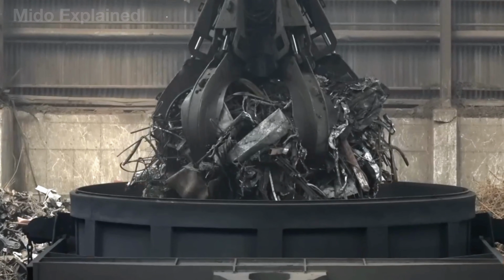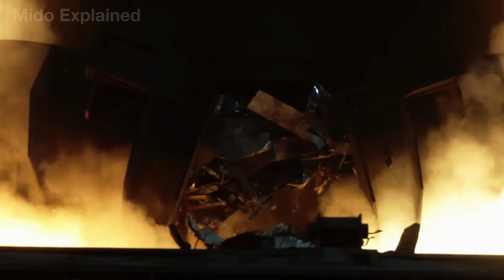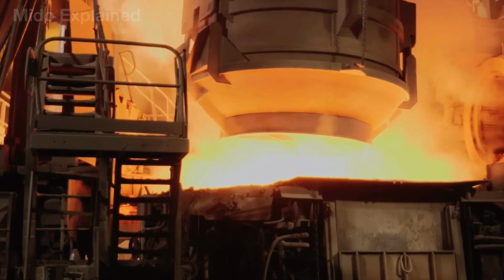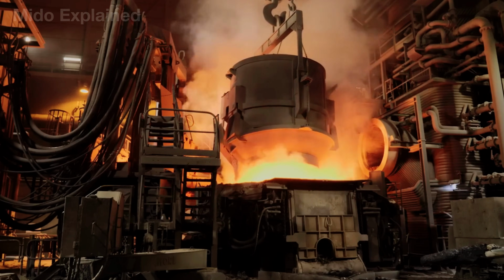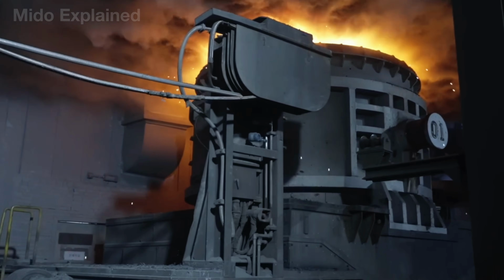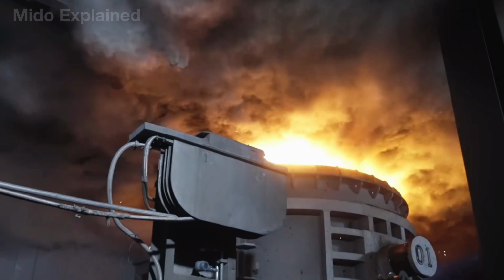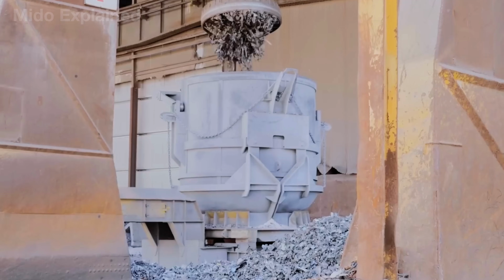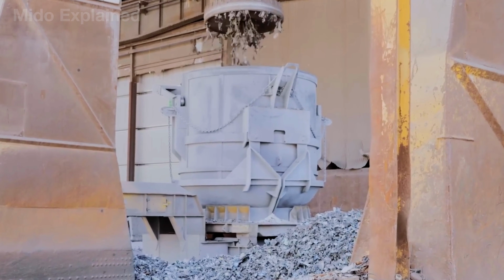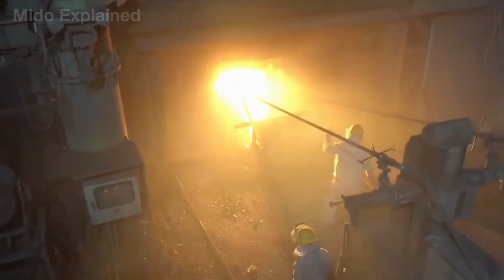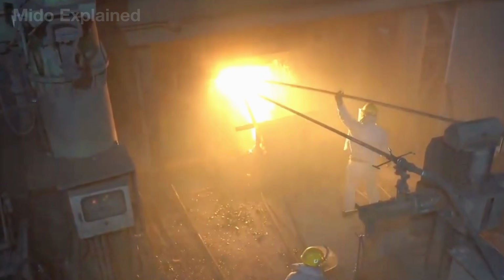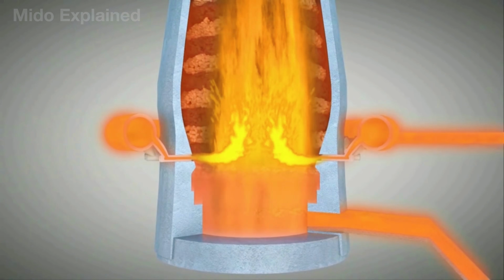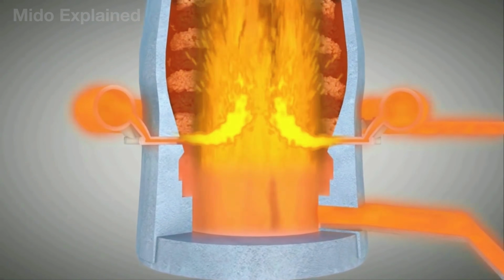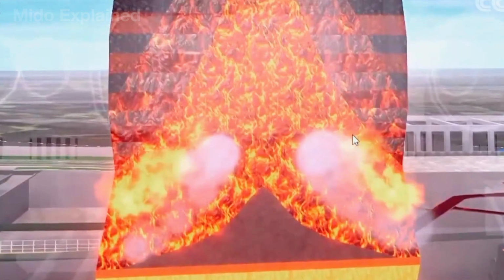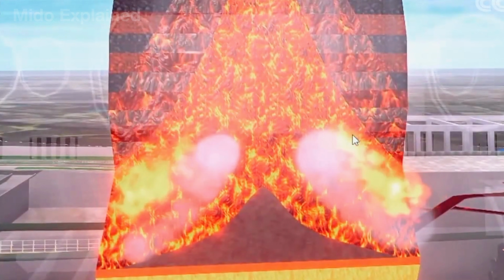A typical furnace can process from 70 to over 200 short tons of steel per batch, and many plants operate dozens of batches continuously each day to meet production demands. When operation begins, the furnace roof opens to allow the scrap steel to be loaded inside. Then, 3 enormous graphite electrodes slowly descend. Currents of up to tens of thousands of amperes are passed through the electrodes, creating extremely powerful electric arcs with temperatures that can exceed 5,000 degrees Fahrenheit.